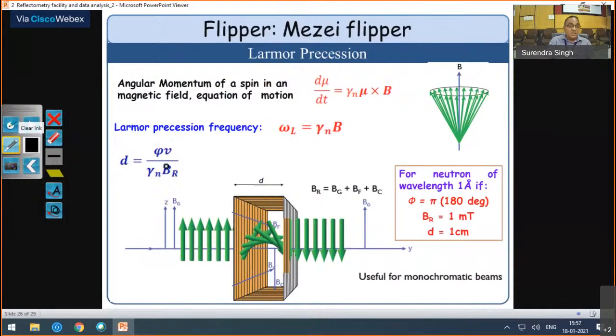What is the distance required to flip the spin of the neutron? Flipping the spin of the neutron means making it 180 degrees, so it is like this. After the flip here, you will get spin down, and again you have the guide field, which will keep that spin of the neutron. If you put the values over here, using a neutron of 1 angstrom, you know the velocity, how to calculate for a 1 angstrom neutron. You calculate the velocity of the neutron, put phi as 180 degrees, and you will see Br equal to 1 millitesla.